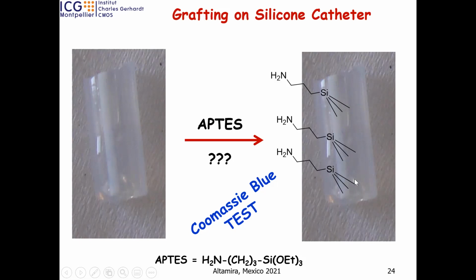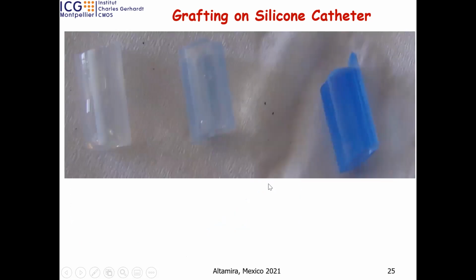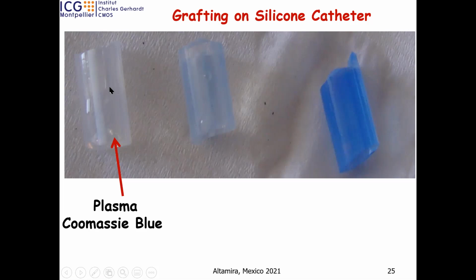You have silicon, oxygen, silicon bond, okay? And we follow this test by Coomassie blue color. First, the catheter here, we took it directly, the catheter, plasma, and Coomassie blue without any grafting, just to show you that our catheter doesn't react with Coomassie blue. There is no adsorption of Coomassie blue on the surface.